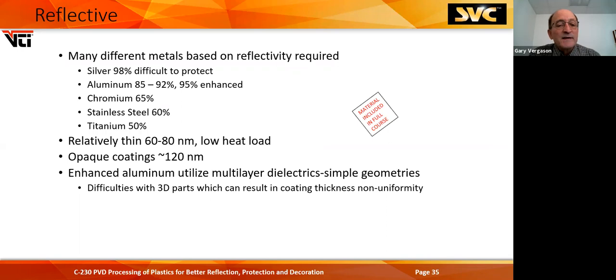Looking at reflective coatings, there's many different metals based on the reflectivity and the color that's required. Silver is very high in reflectivity, but difficult to protect from corrosion. Depends on where the part is. Most of the parts that we coat are outside.